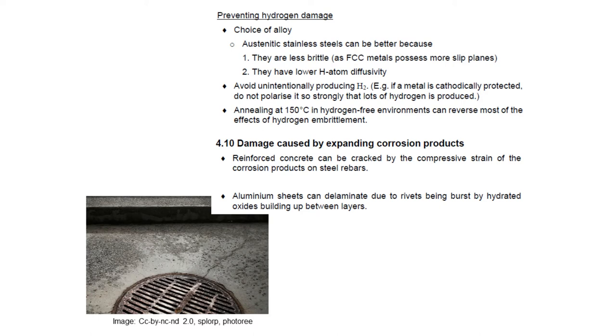A particularly important case is aluminium aircraft, where sheets of aluminium can delaminate if corrosion layers build up between them. Hydrated aluminium oxide has a much larger volume than the initial metal, producing tensile stresses in rivets holding the aluminium sheets together. This can lead to failure of the aircraft exterior and must be identified during maintenance inspections.